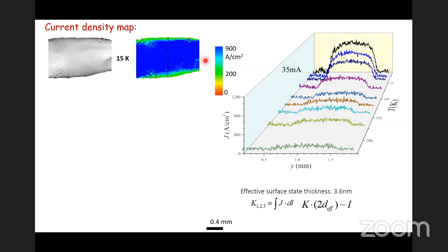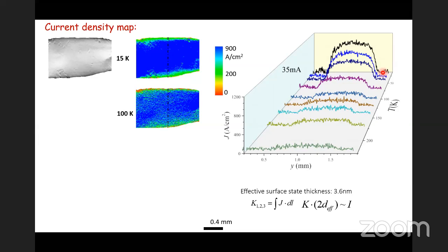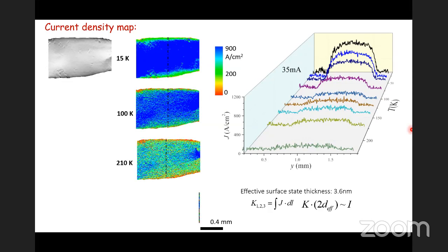But now as you increase the temperature and keep on measuring the current, you see that the current on the surface progressively decreases. As you increase the temperature, the height of this current density on the surface actually goes down. And if I image this current density, you see something quite amazing: the current actually not only decreases in strength, but it starts breaking up into patches. There are patches of blue regions which are high current carrying regions, but there are lower conductivity regions which are appearing in the sample. And as you increase the temperature, it becomes more and more. So the region which has uniform high current density starts breaking up into patches, and the amount of current on the surface starts decreasing.